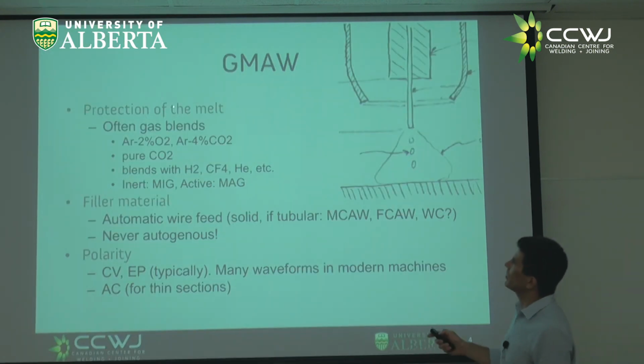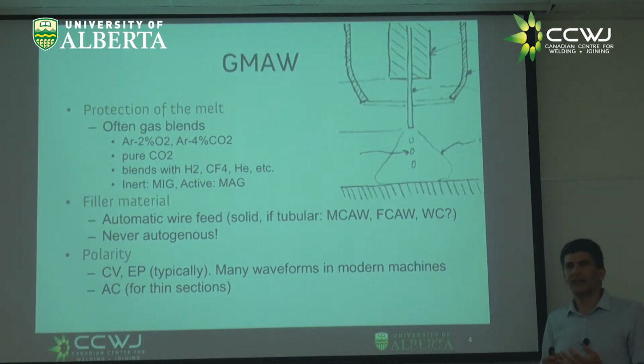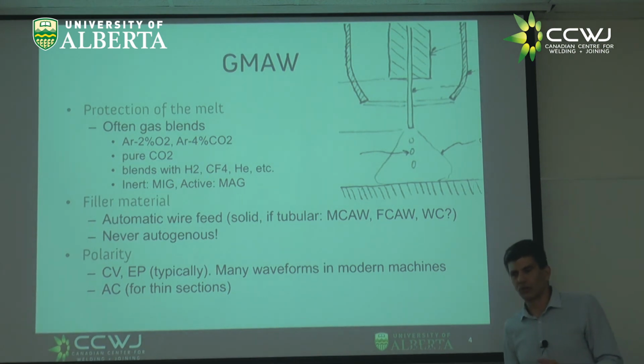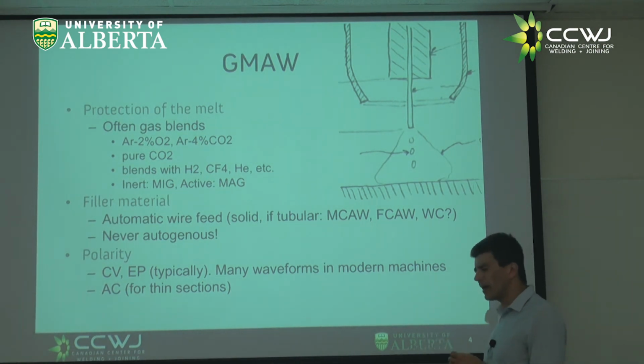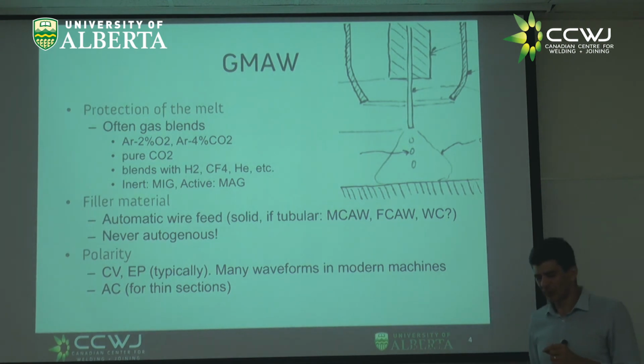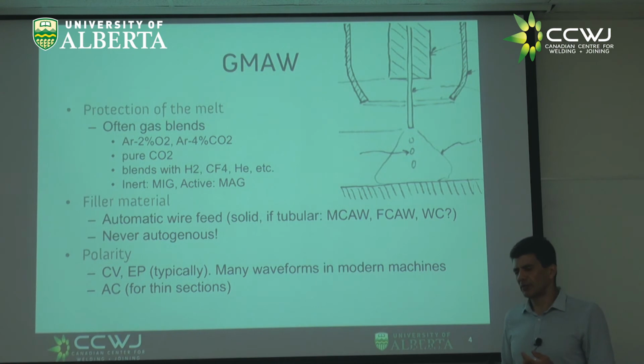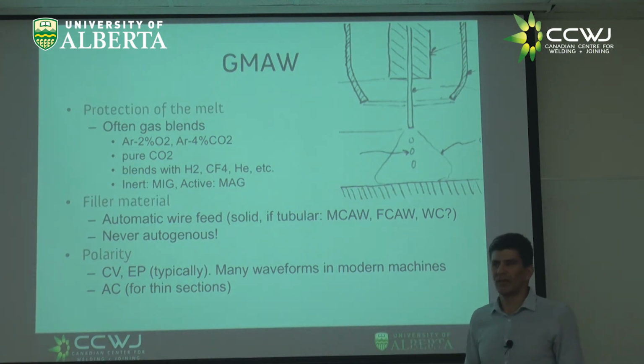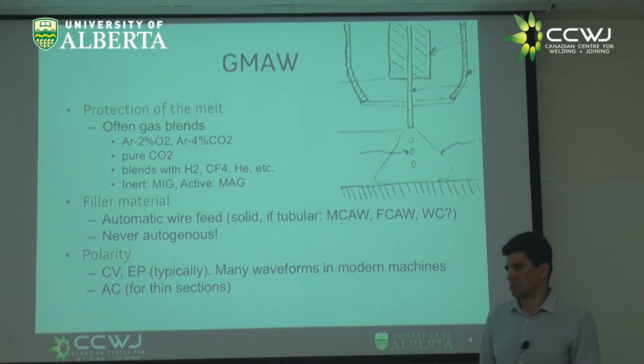Okay, so protection of the melt. In TIG and plasma, we typically use pure argon. But now in MIG, we use other blends. There are good reasons for this. One reason is if I put anything that is oxidizing with a tungsten, I'm going to ruin my tungsten, so that's bad. But in the case of MIG, I'm melting the electrode constantly, so it doesn't matter if I oxidize my electrode. The electrode keeps melting, so my problem is in the weld, but not anymore in the electrode.